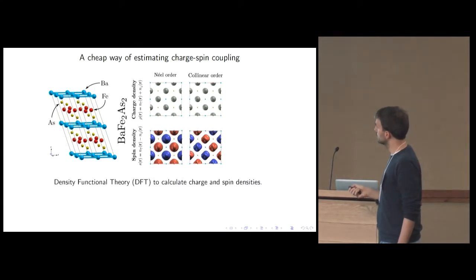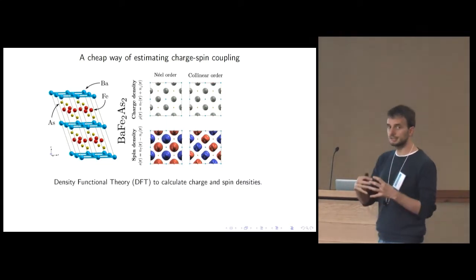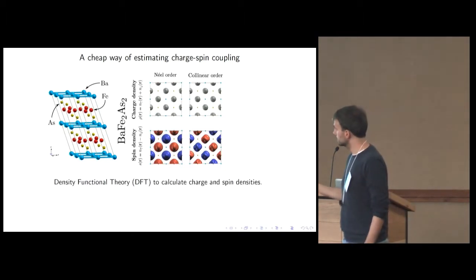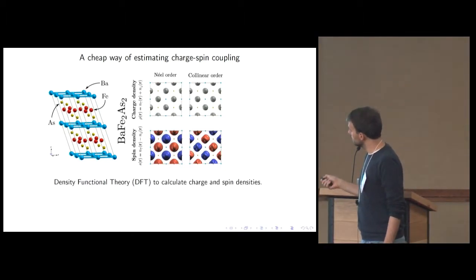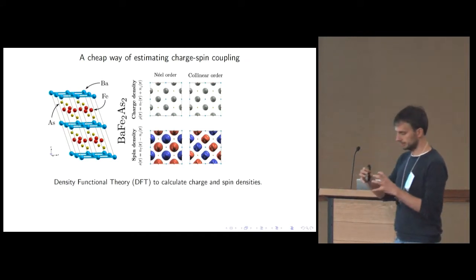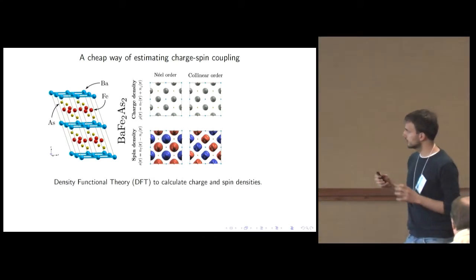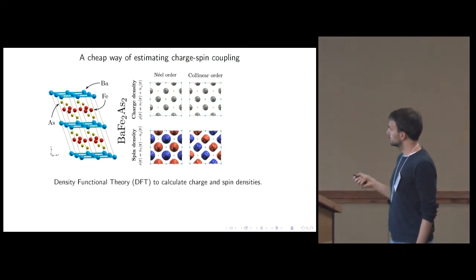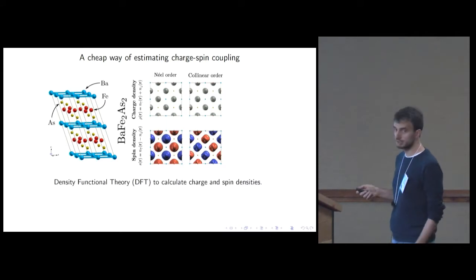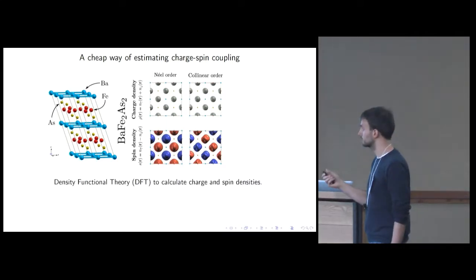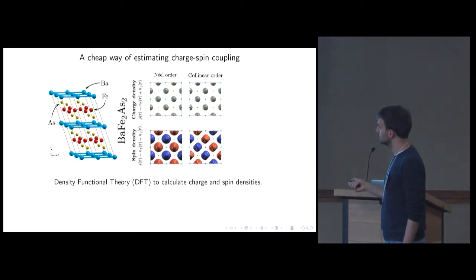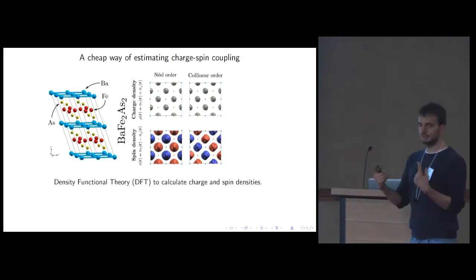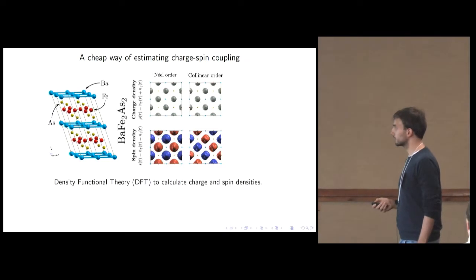On the top panel, we are looking at the charge density in this layer, and at the bottom, the spin density. The small points here are essentially the atoms. The colors are the same. The irons are really inside these iso-density charge density spheres. The two columns stand for two different magnetic orders, where here we have the stripe order that I was just telling you about, that is the ground state in this particular system. And here we have an excited state order, this antiferromagnetic Néel order.